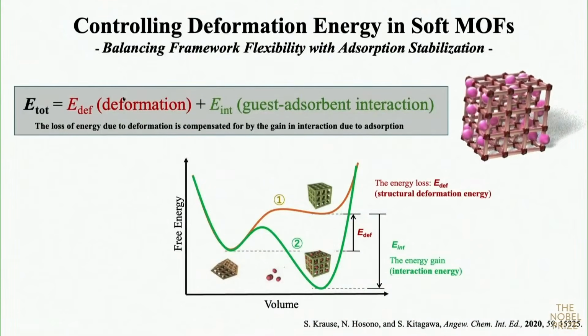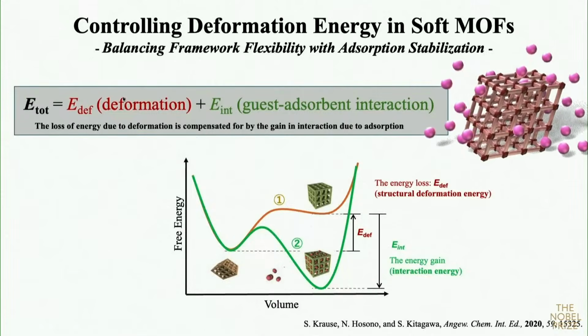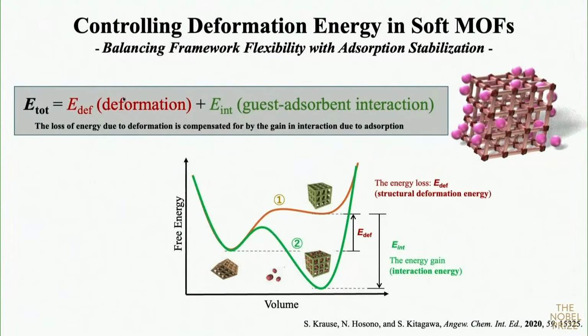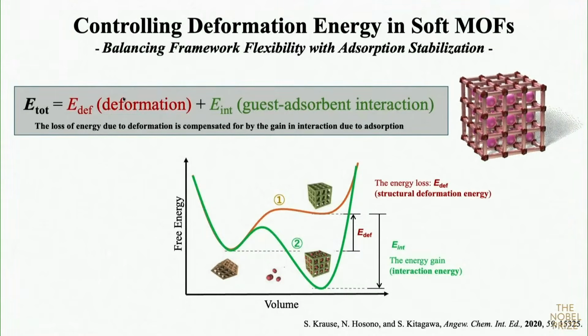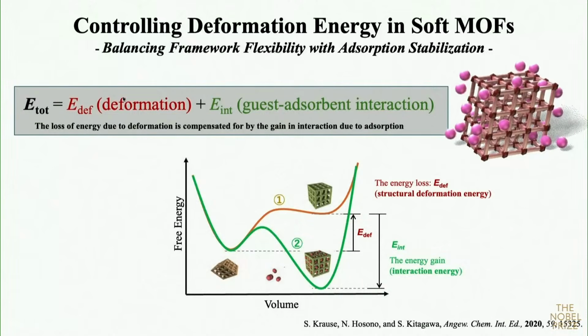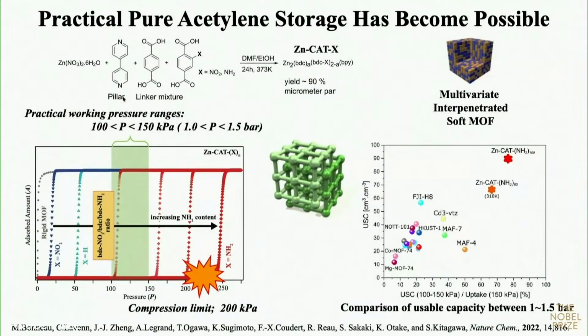Our strategy is this: the structure should change to accommodate gas molecules, so the deformation energy control is very important. Here, in the interpenetrated structure, the unit has zinc, benzene dicarboxylate and pyridine. To control the deformation energy, we introduce substituents, just like a solid solution structure. Finally, we obtained this beautiful sorption. The pressure range is larger than 1 bar and lower than 1.5 bar. A very safe storage system we can get.